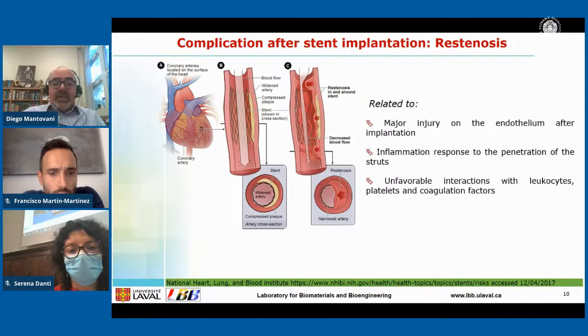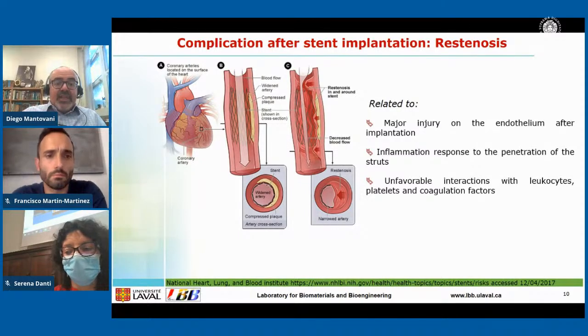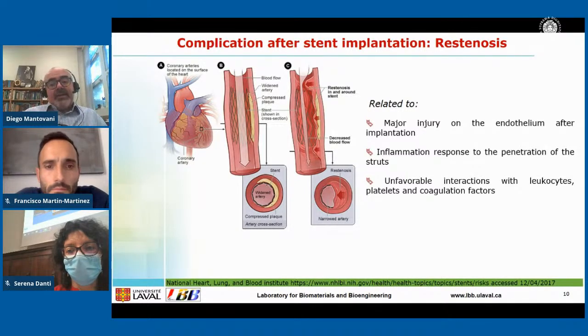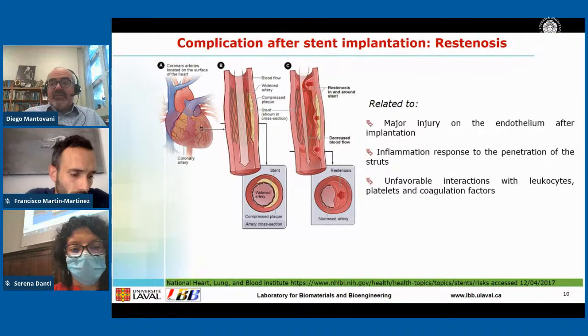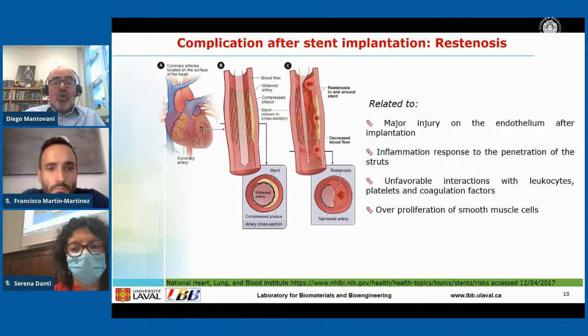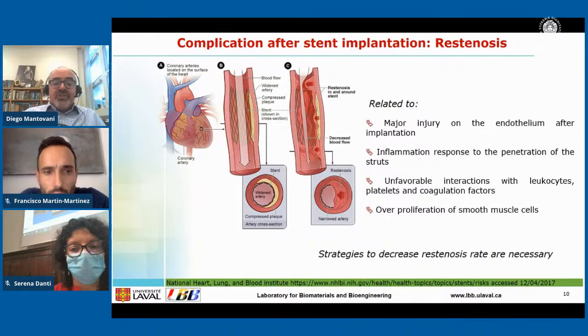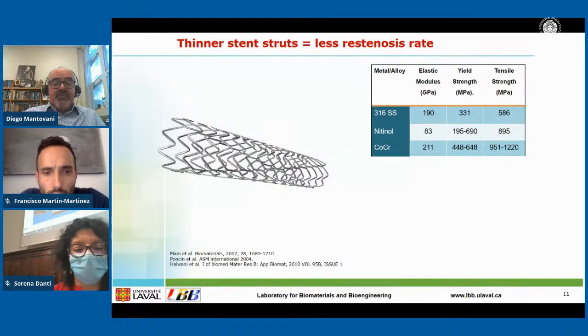As you can see here, the stent, when implanted, will not remain only deposited on the intimal layer, but it will enter and break part of the intima and reach, in general, the media and even sometimes the adventitia. So there is an uncontrolled proliferation of smooth muscle cells called in-stent restenosis. Strategies to decrease this restenosis rate are necessary.